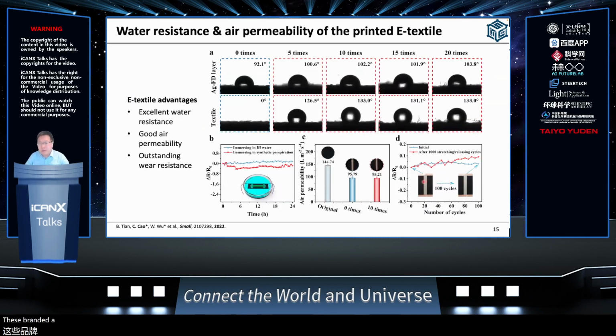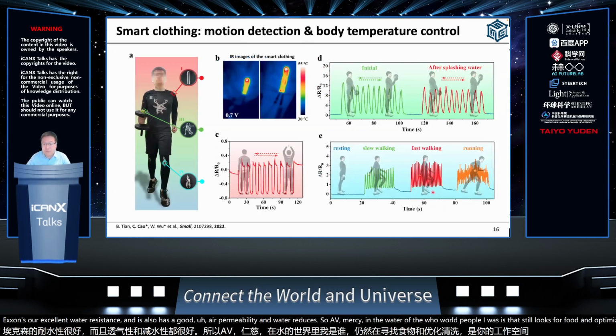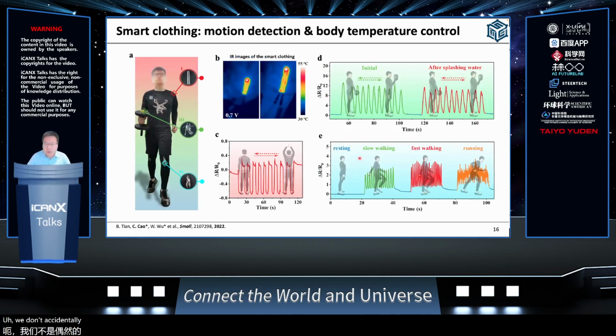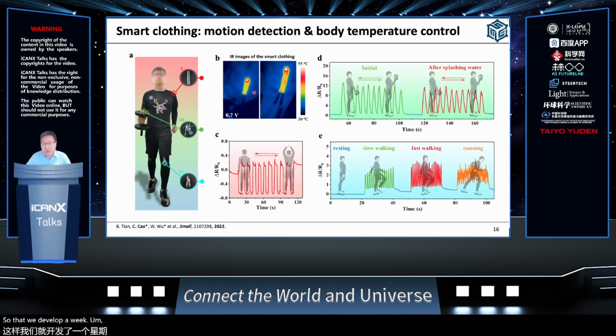These printed textiles have excellent water resistance, and also good air permeability. Even when immersed in water for over 24 hours, they still work quite well, and after multiple washing rounds, they still work quite well. With the excellent electrical performance of the e-textile, we can fabricate aesthetic smart clothing. We can build a dual heater using the e-textile embedded in the clothes to help manage body temperature. The strain sensors can be used for monitoring the motion states of the user, and their performance will not be affected by sweat and water.